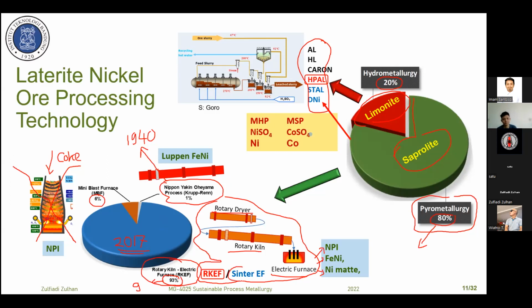Another technology is the sinter electric furnace. In this kind of technology, they replace the rotary dryer and the rotary kiln with a sinter machine. The nickel ore is sent to the sinter plant. It's mixed with calcium oxide and mixed with coke as fuel to produce sinter, and then sent to the electric furnace for smelting. We mix with coke or semi-coke or anthracite as a reductant, and then we send it to the electric furnace.